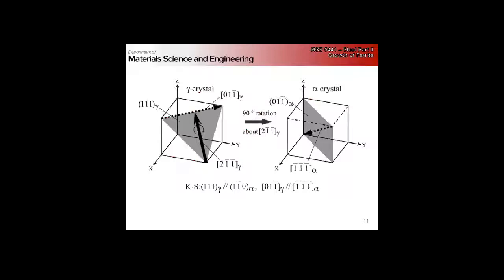We have the 1-1-1 plane on the gamma parallel to a 1-1-0 type plane in the ferrite, and the close-packed directions lining up. So basically this can be envisioned as a 90-degree rotation about a [2 1 1] direction, and it's worthwhile to take the time to sketch out these planes, exactly what is related to what.